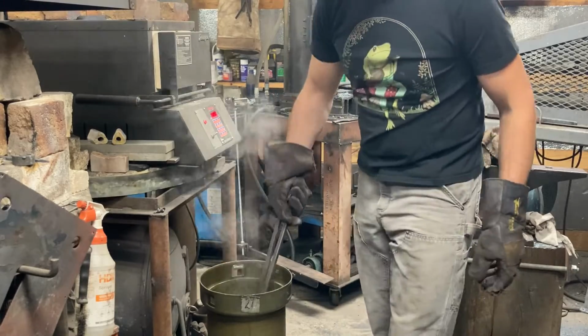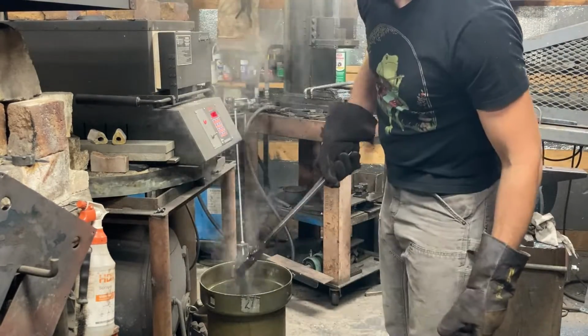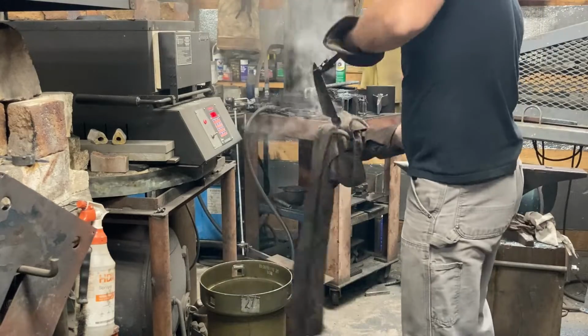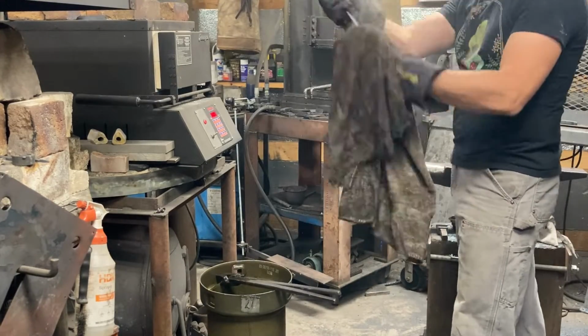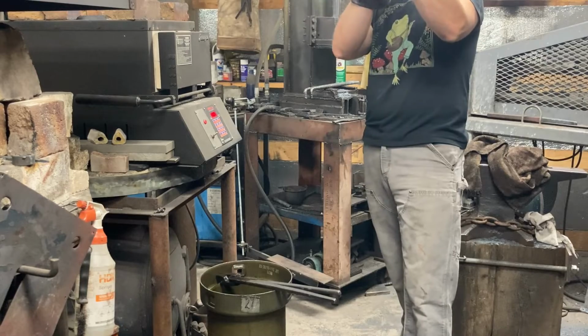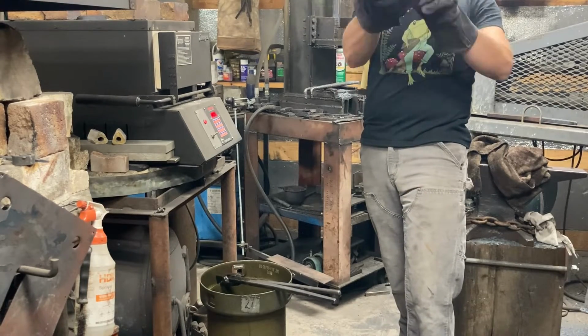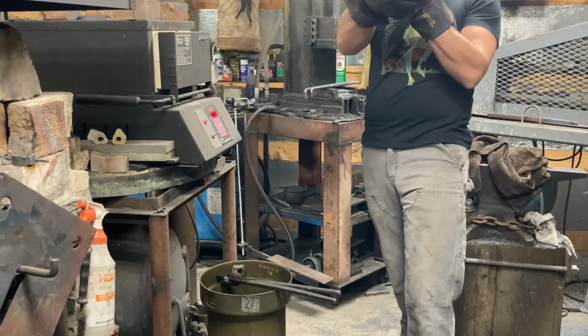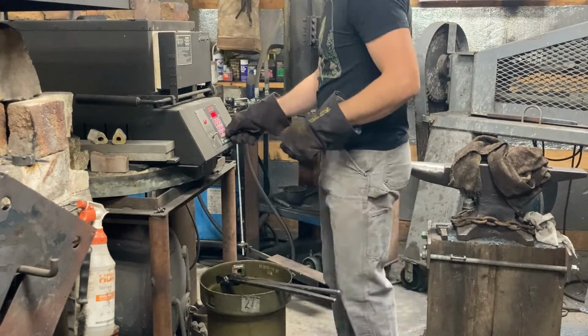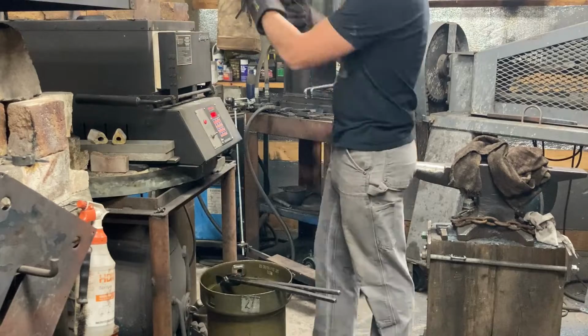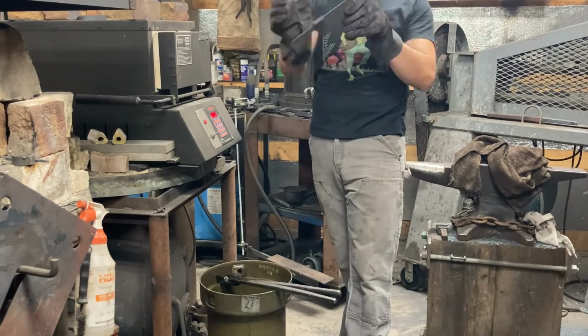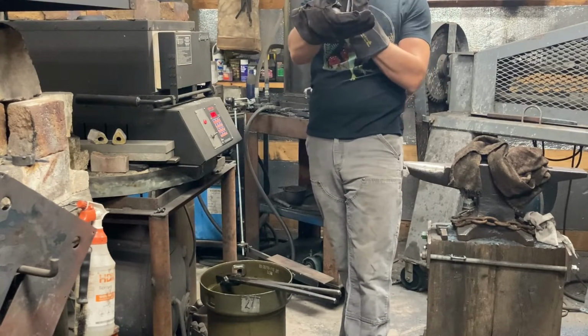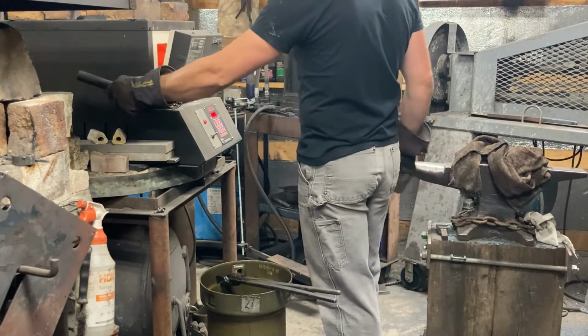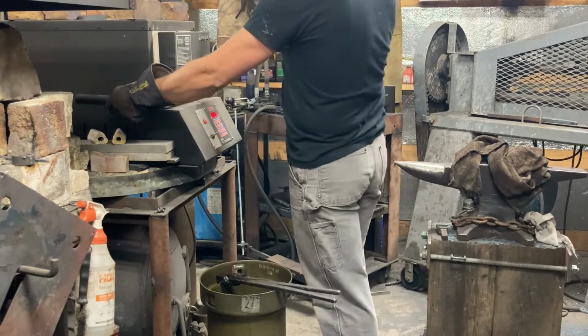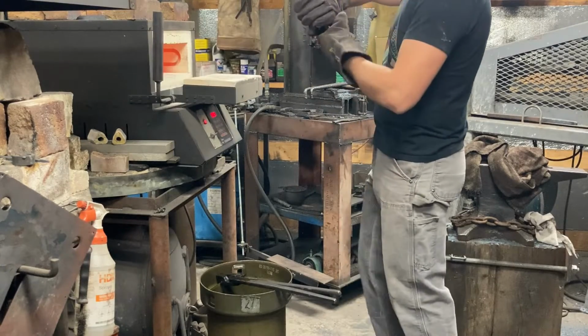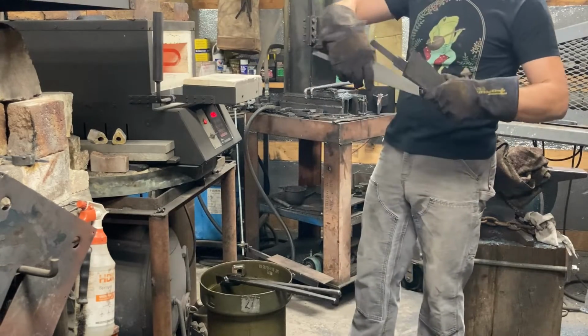Here I'm doing the second one at super speed. Flip it, grab the bolster, mop it off, and hold it up, sight down it, find any kinks in the blade, or if the tang is bent in relation to the blade, anything like that, and quickly try to straighten them, and then set them aside to cool. As soon as they cool down enough to room temperature, I'll put them right into temper. So I'm going to go throw these into a 300-degree snap temper in the house while I'm dumping heat out of the Paragon. Thanks for watching this far, and then stay with me for the next installment.